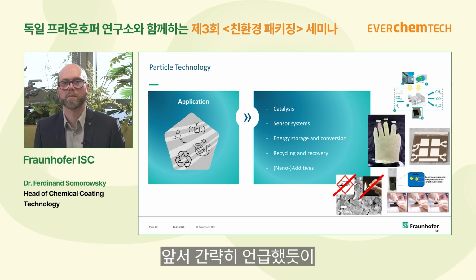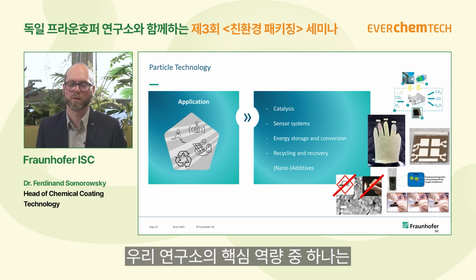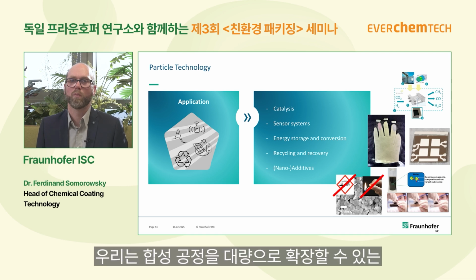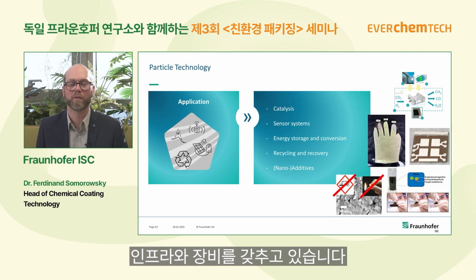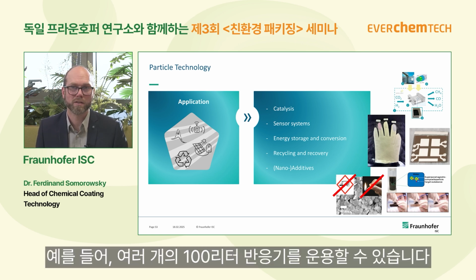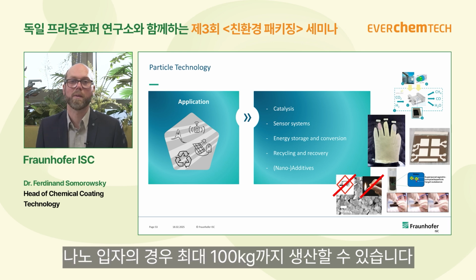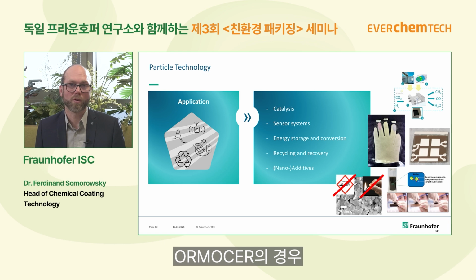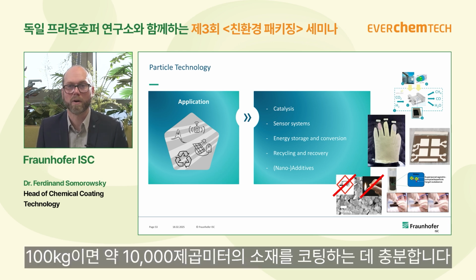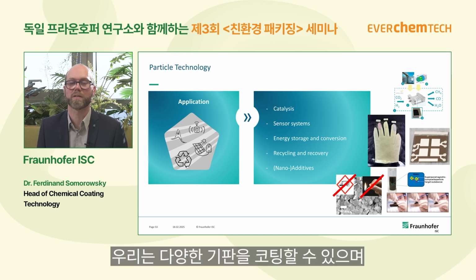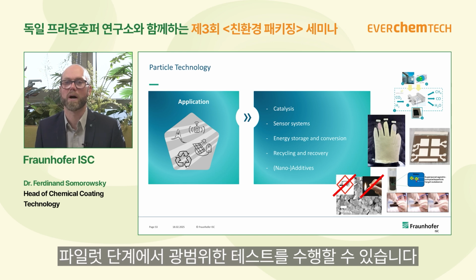I mentioned it a little bit, but one competence of our institute is also the upscaling of material. We have the possibility and the equipment to upscale, for example, the synthesis. We have several 100-liter reactors to produce lacquers, for example, or nanoparticles on the 100 kilogram scale. And when we look at the Ormocer, 100 kilograms are enough to coat around 10,000 square meters of material, so we can really coat a lot of substrates and test a lot in the pilot phase.